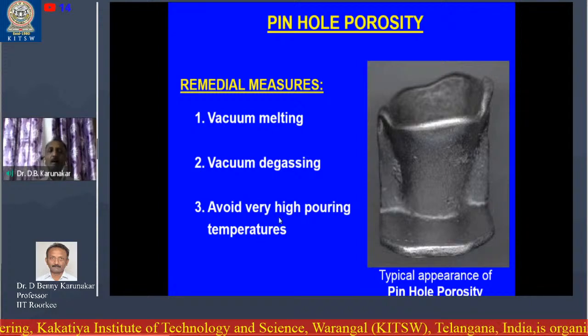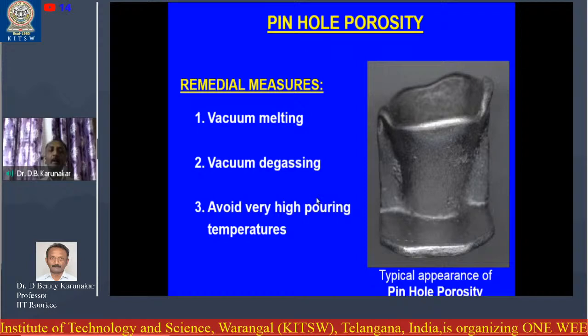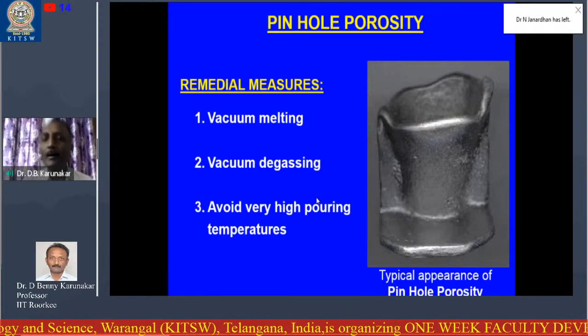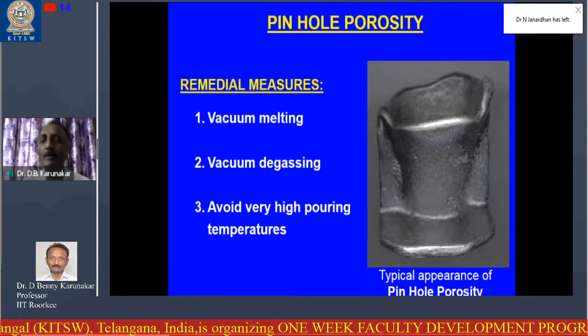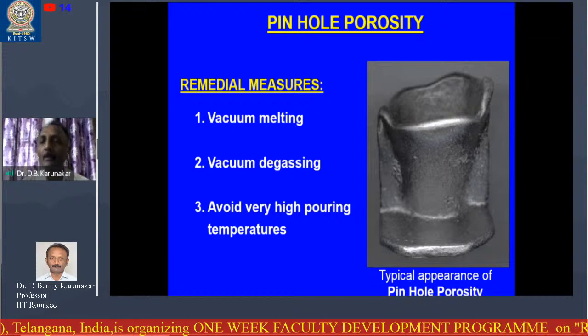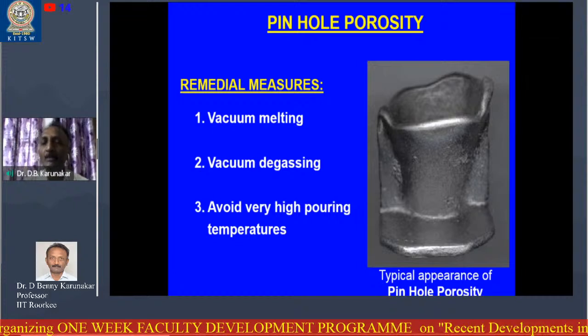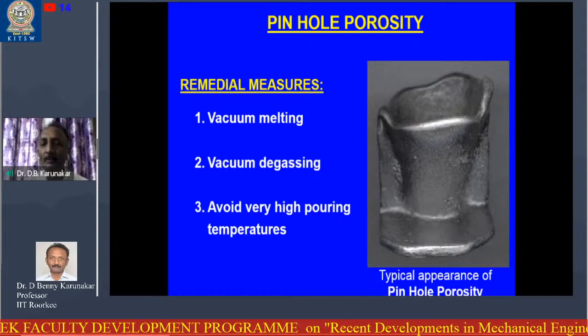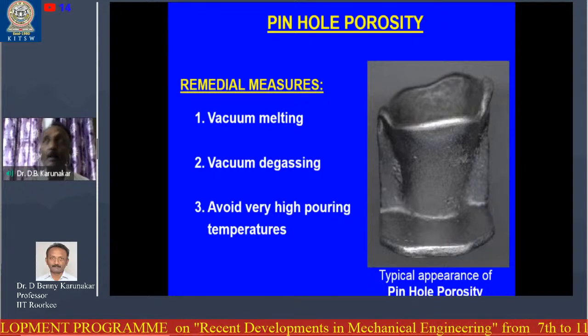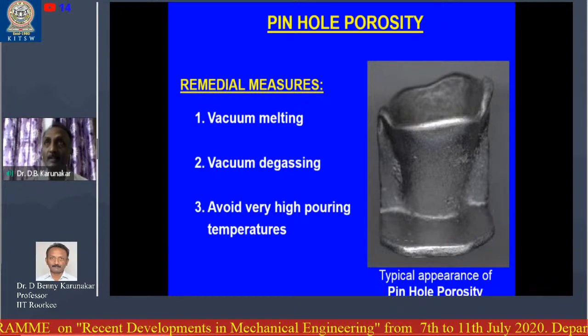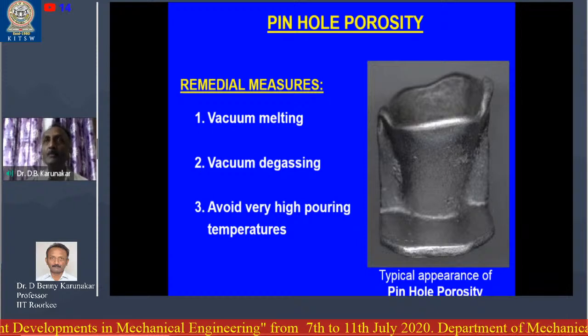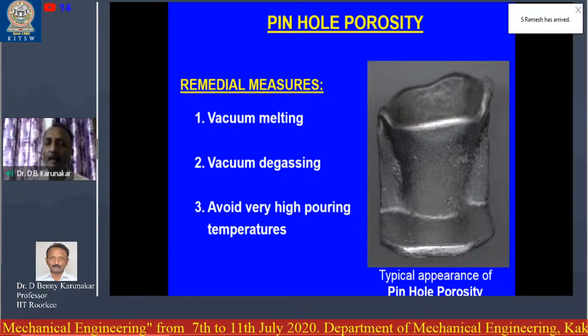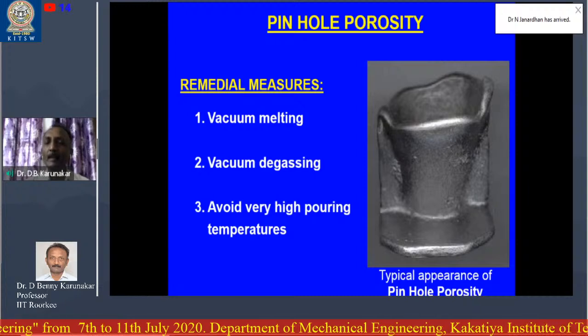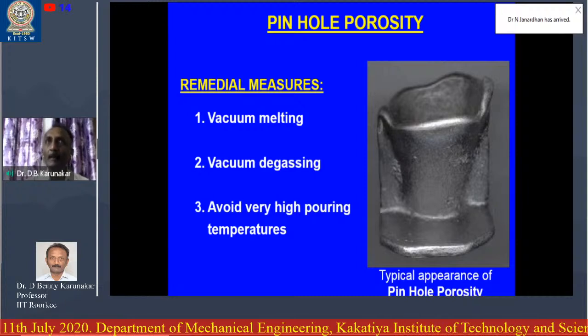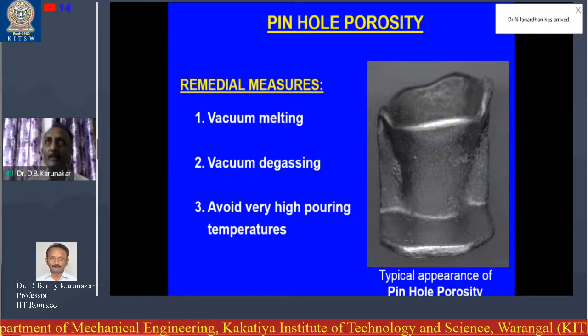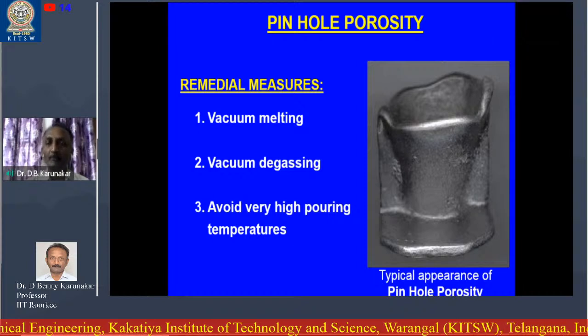Next, avoid very high pouring temperatures. We always give superheating. For example, the melting point of aluminum is 660 degrees centigrade. So beyond 660 degrees melting temperature, we heat by another superheat, maybe 75 degrees more, up to 725 degrees, or in the worst case up to 750 degrees centigrade.